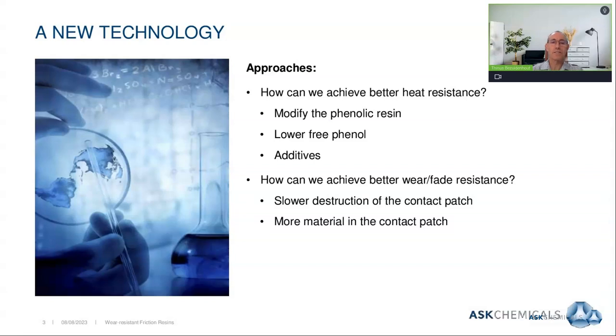This next slide is to discuss the conventional ways that we would normally manipulate phenolic resins to get a better wear or heat resistance. You would know from normal conventional knowledge that phenolic resins are often modified, and these can be various modifications such as epoxy modification, rubber modifications, metal modifications, or cashew oil modifications, but also one can manipulate the residual phenol monomer levels that are left in the resin. And lastly, one can also use additives to manipulate the resin.